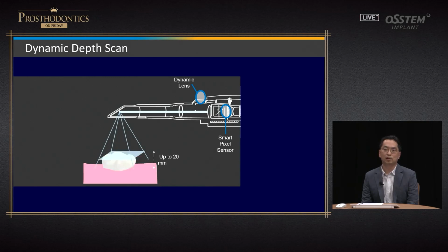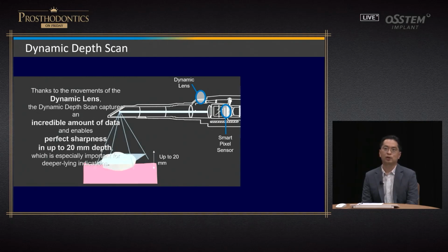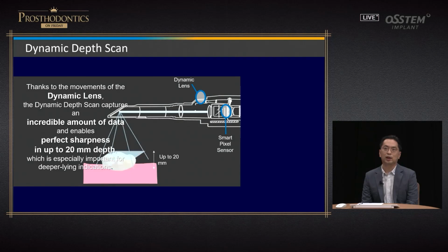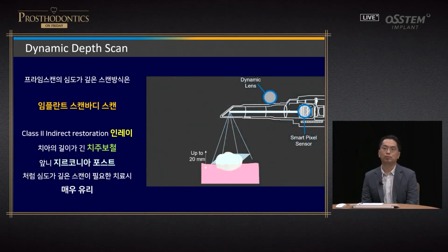Dentsply Sirona introduced Prime Scan. This offers dynamic depth scan function. It can measure up to 20 millimeter. With dynamic depth scan, it is now possible to scan implant scan body and class 2 indirect restoration inlay, the periodontic prosthesis with long teeth, zirconia post for the interior teeth, and others in a very easy manner.